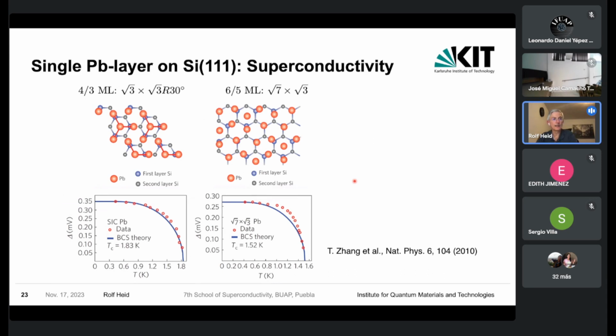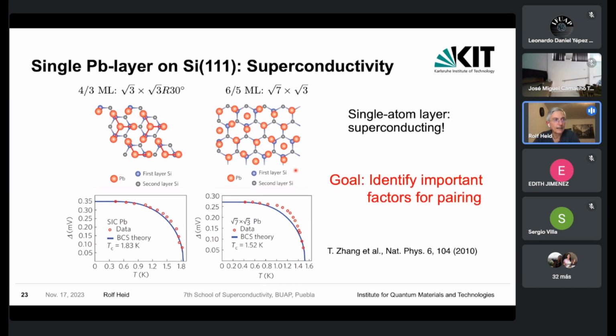Now, the surprise actually came in this work that these single atom layers are still superconducting. So you can see here the measurements of the gap as a function of temperature, showing a transition temperature in this case of 1.83 Kelvin, and here a little bit lower, 1.5. So it really came as a surprise that the superconductivity survives this limit. The goal of our investigations was to try to identify the important factors which lead to this specific kind of pairing interaction, which still renders these single atomic layers superconducting.